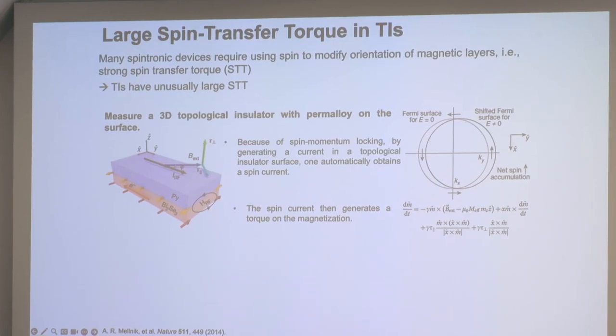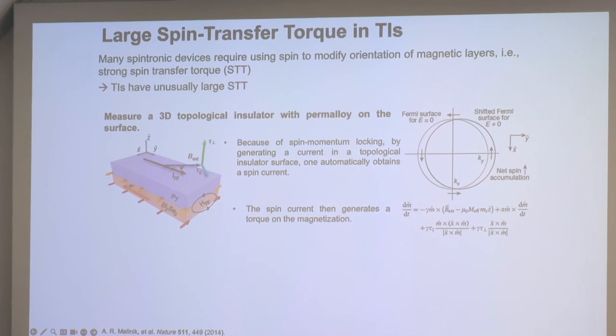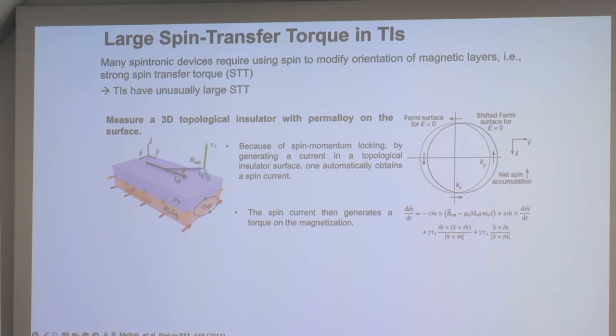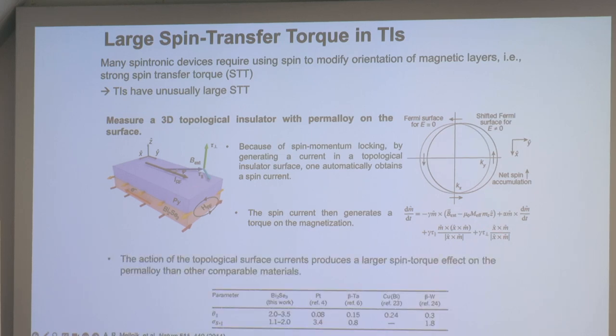The spin current then generates a torque. This is the Landau-Lifshitz-Gilbert-Slonczewski equations, which are standard for looking at the effect of a spin in a magnetic material. So it generates a torque on the magnetization in the permalloy. And this was measured using spin transfer ferromagnetic resonance. They use an AC current in the bismuth selenide and measure the resonance of the spins in the permalloy. Using this technique, they could measure that TIs have a much larger spin torque effect than other heavy metal materials, which are typically used.